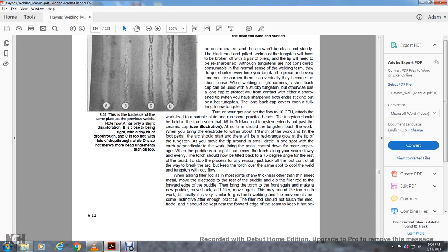When you bring the electrode to within 1/8 of an inch of the work, hit the foot pedal and the arc should start. There will be a red-orange glow at the tip of the tungsten as you move the tip in a small circle in one spot, with the torch perpendicular to the work. Bring the pedal control down for more amperage. When the puddle is bright and fluid, move the torch along your seam slowly and evenly. The torch should now be tilted back at a 75-degree angle to the rest of the bead.